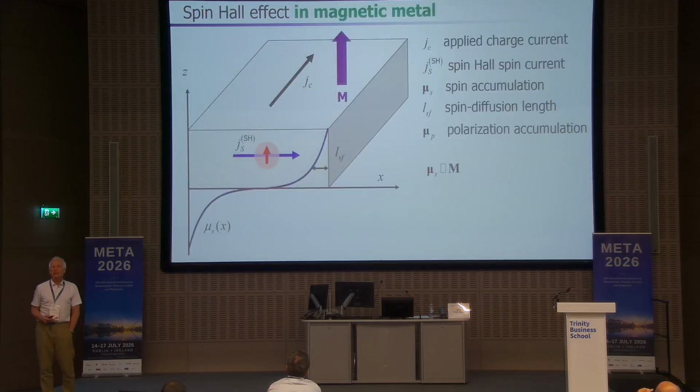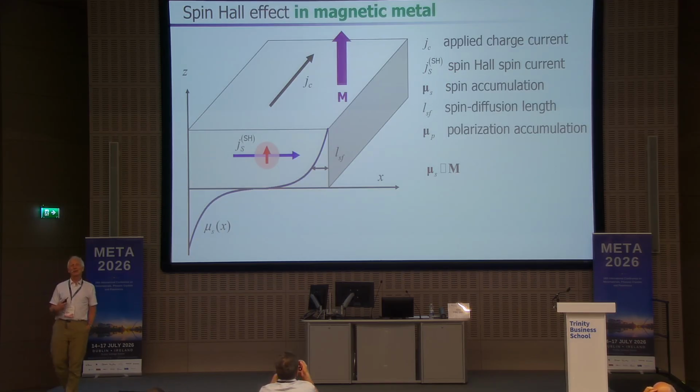So what is happening here? Now, that is maybe a bit specific, but it is due to the spin Hall effect in the ferromagnetic metal. The spin Hall effect generates transverse spin currents, and these spin currents must be polarized along the magnetization, which we assume to be normal. Now, the conductivity of upspin and downspin is different in a ferromagnet, so these spin currents are coupled to the charge, and they generate a charge polarization accumulation at the edges of this material.